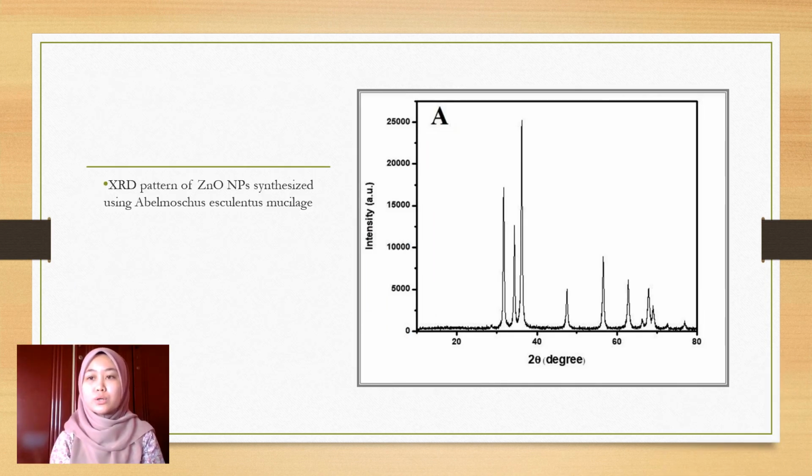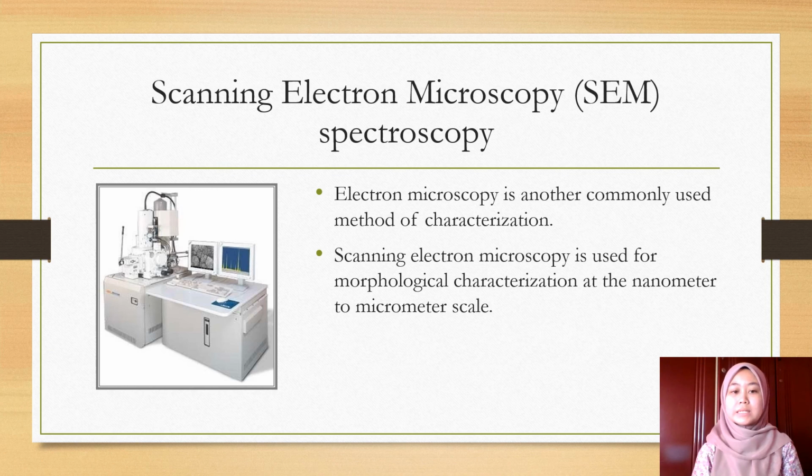This slide shows the XRD pattern of zinc oxide nanoparticles synthesized by using Abelmoschus esculentus mucilage. In this graph, the highly intense and sharp diffraction peaks demonstrate the high degree of crystallinity and purity of the nanoparticles without any secondary phases. Third is scanning electron microscopy.